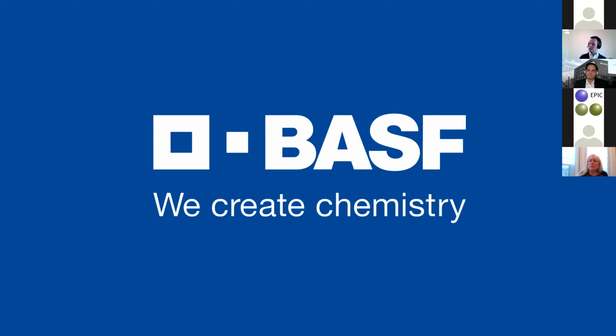Okay, but when it is in the sun for such a long period of time, do you see the optical effects like yellowing and index more critical, or is there also a problem with the adhesion between substrate and the lacquer? That's hard to say definitively without knowing exactly the buildup which you are using. But if I have to guess, I would say adhesion, because it depends on the foil you're using.